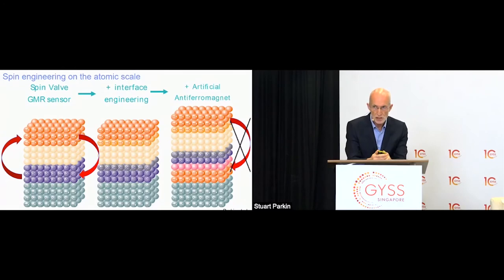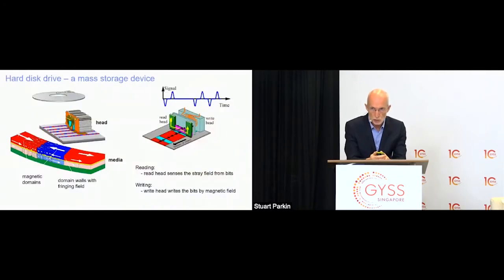And the very first device that was introduced into a magnetic recording head by IBM used exactly this structure that I invented, a synthetic antiferromagnet stabilized by exchange bias with an antiferromagnet, a copper layer, and interface layers designed to optimize the magnitude of the giant magnetoresistance. And basically, we design a structure in which the two magnetic layers have their moments opposed orthogonally to